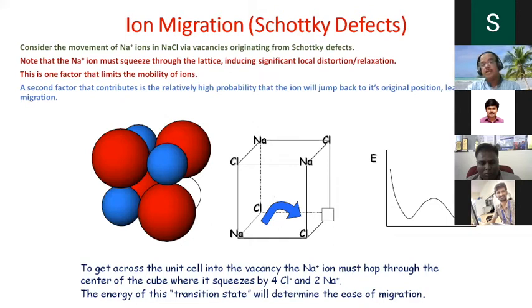So this is the same thing for Schottky defects. So what's the movement of sodium ions in sodium chloride? By vacancies originating from Schottky defects. Which means that the sodium ion must squeeze through the lattice, inducing significant lattice distortion or relaxations. So if it is unable to cross that bottleneck, then that is the factor that limits the mobility of ions. So if unable to jump, then it goes back to the original position, leading to no net ionic migration. So the transition state would determine the ease of migration. So defects are essential if you really want to think about conduction as far as crystalline material is concerned.